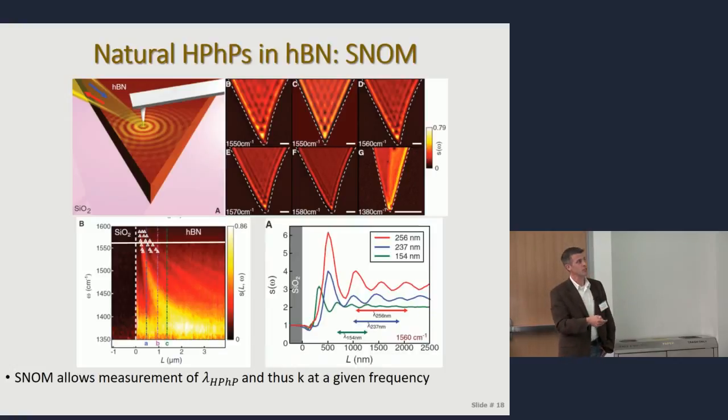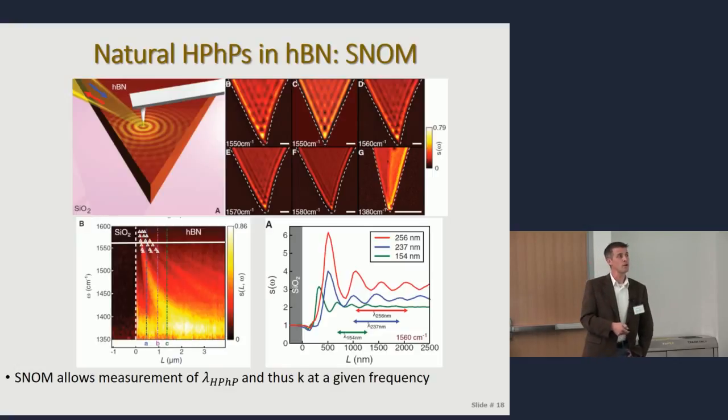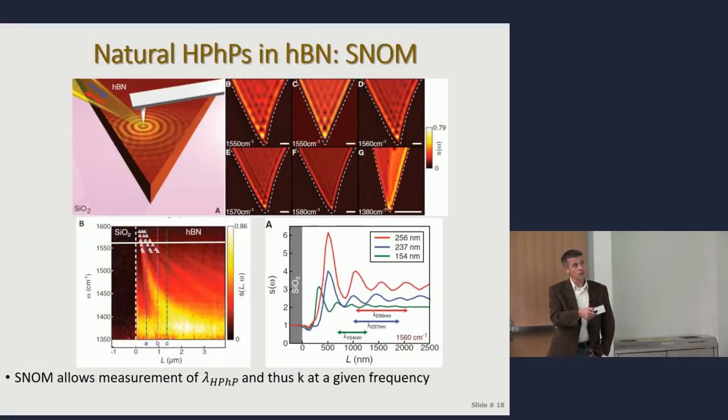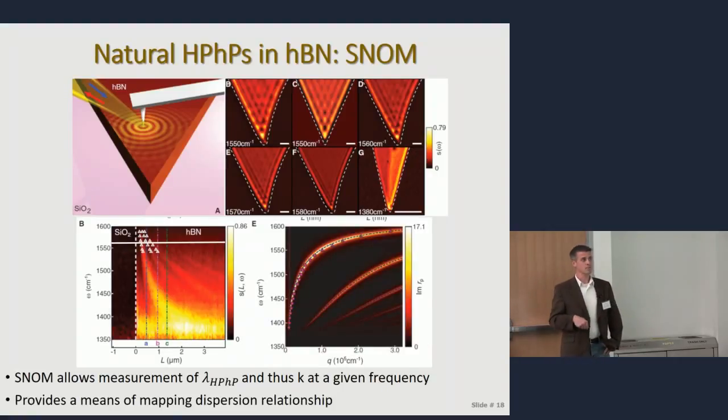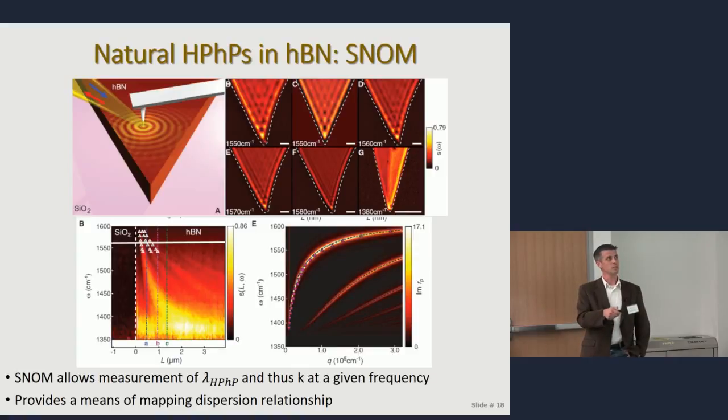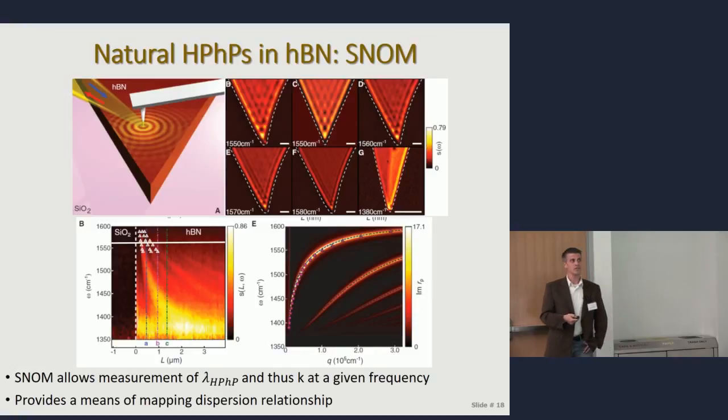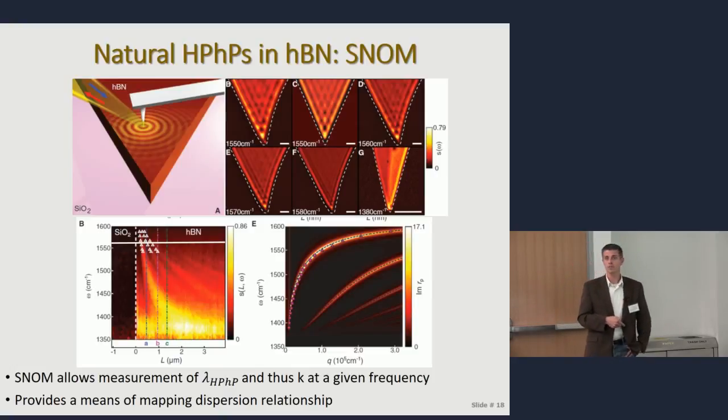And you see something really interesting. Of course, I draw a line through it at a given frequency. As I look at different thickness flakes, I get these different wavelengths. And again, if I measure from here to here, that's my polariton wavelength, right? So then I could take that, take the inverse, and compare that to the incident frequency, and I get my dispersion curve just like I had in graphene. But there's something else here, right? You do the calculation for this, and I have all these additional branches. I no longer just have a single dispersion curve, right?